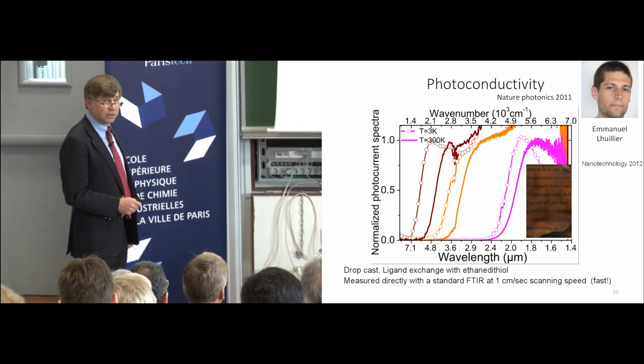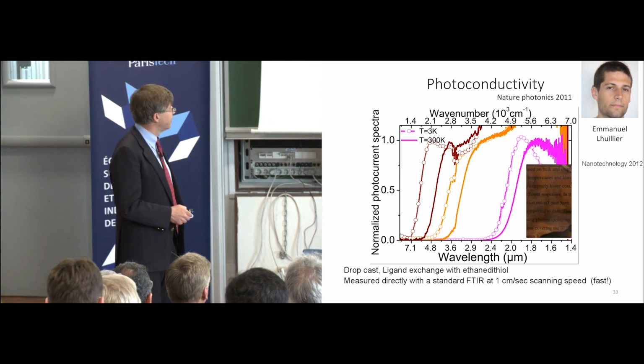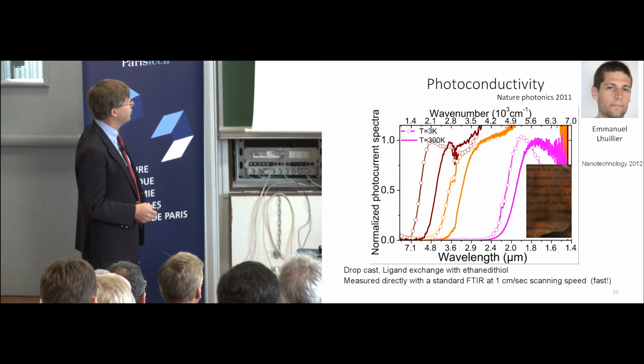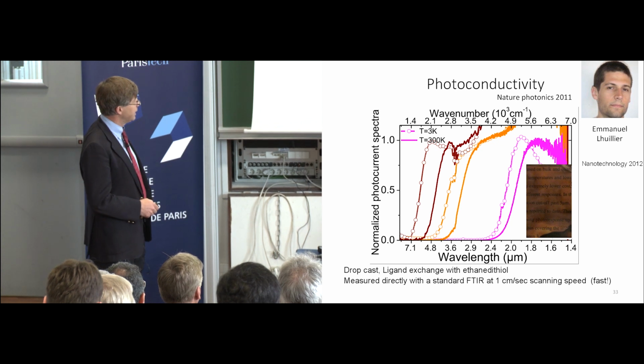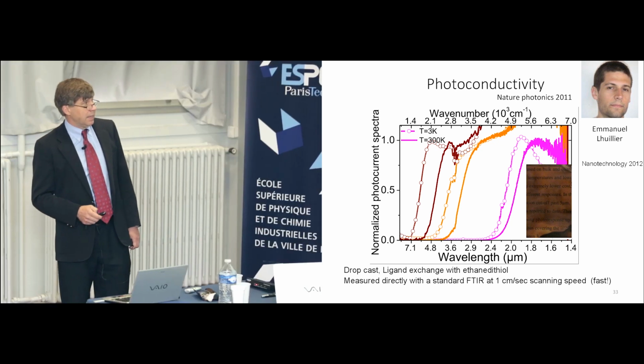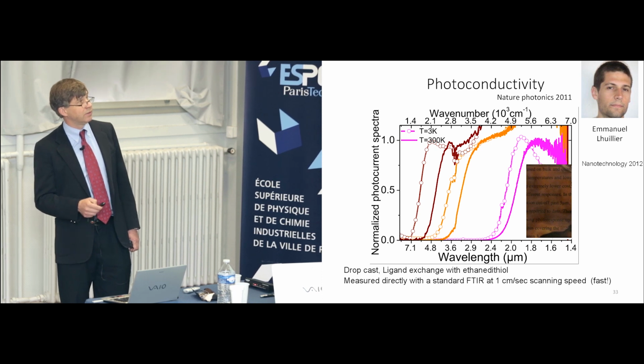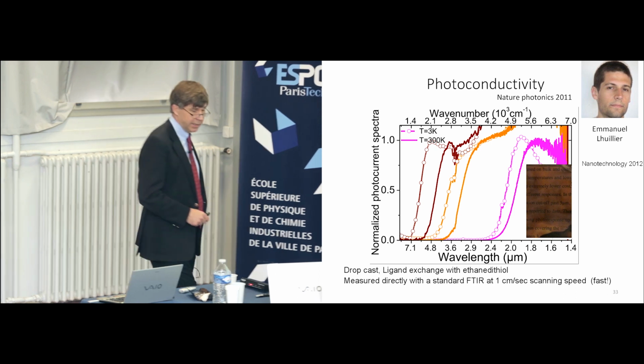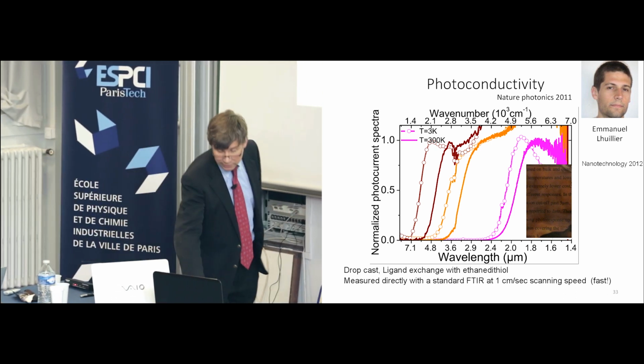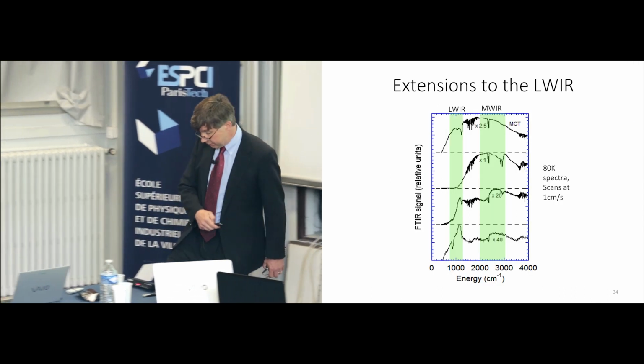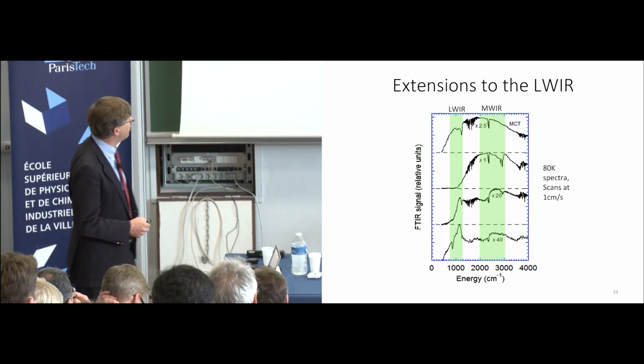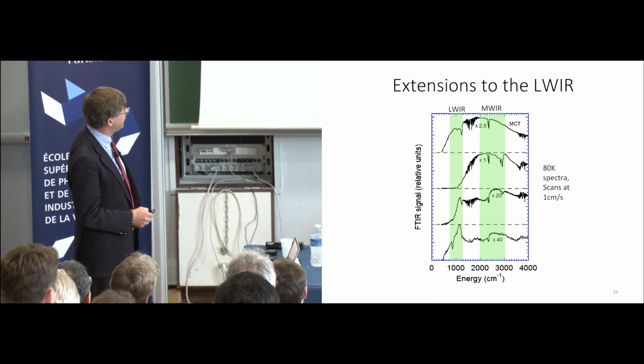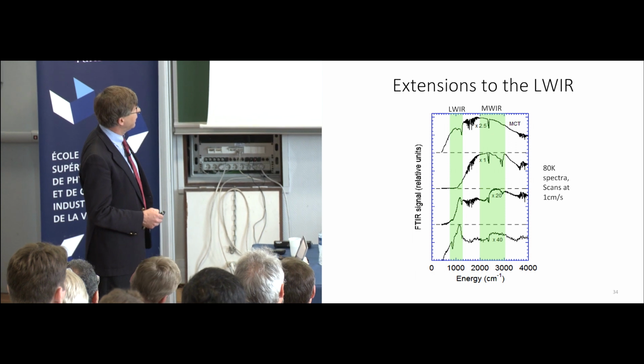So the white light of the interferometer goes through in about 100 microseconds. So they're a very good detector. He characterized, of course, the response speed. You can find that information in his paper there. So that worked pretty well. This is just on the edge of the mid-infrared. This is smack into the mid-infrared. This is extended a little bit further down to 7 micron at low temperature. We extended this a little bit further since he left. Now we can go further into the long wave IR. So this is a dot that responds pretty nicely.